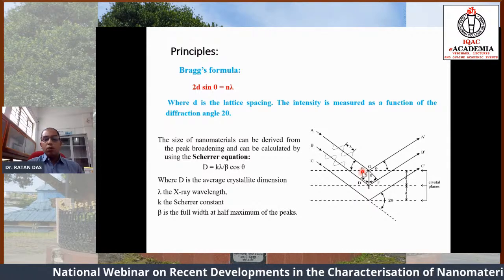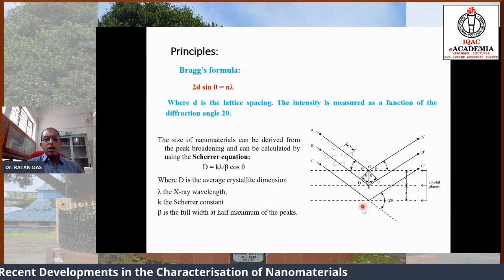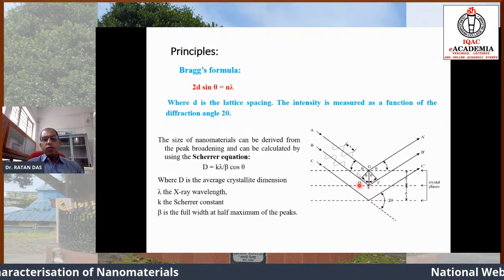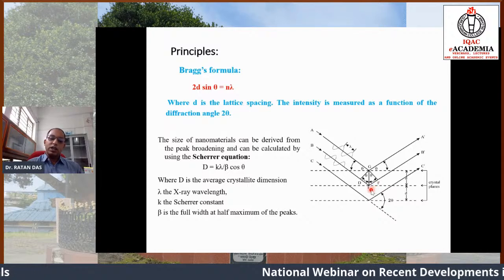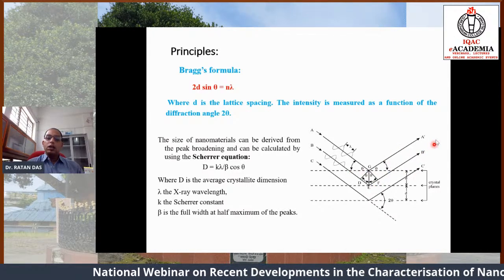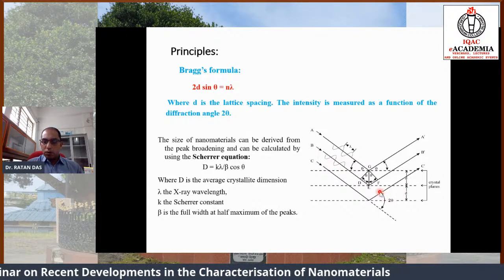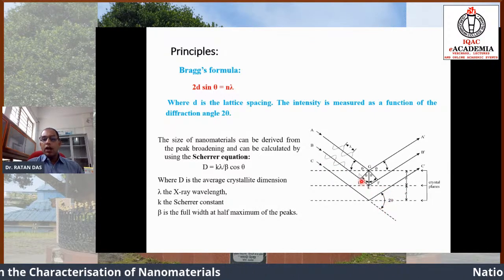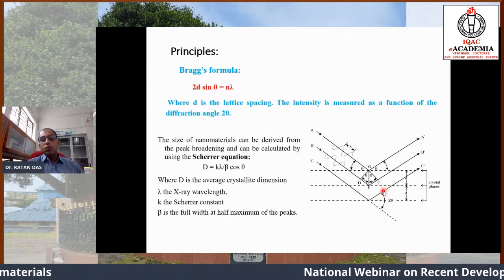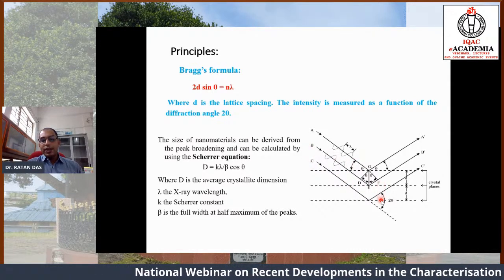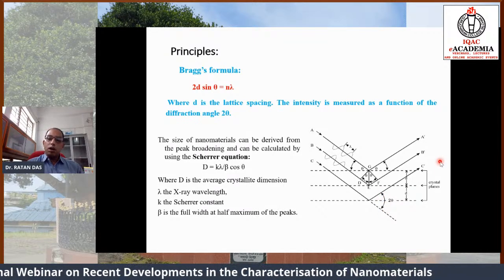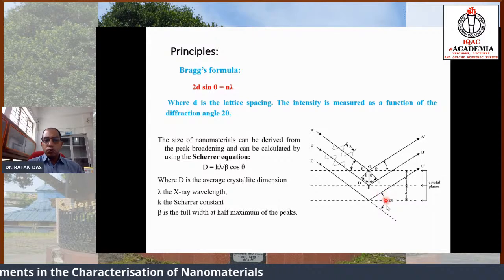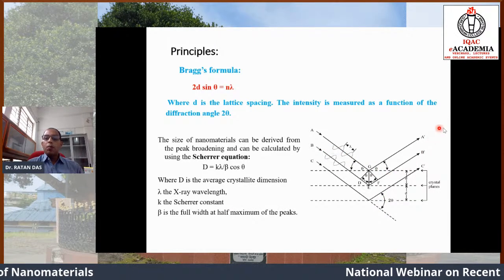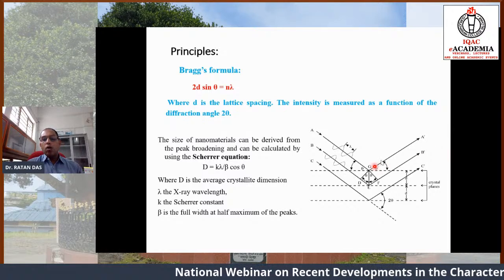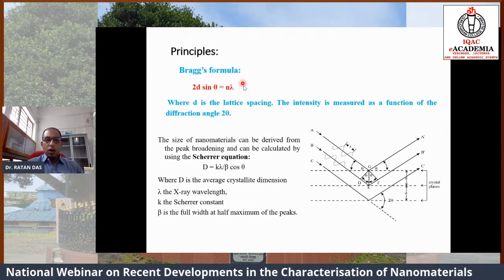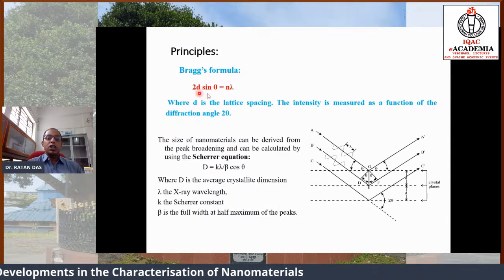The planes may be 110, or 100, or any pattern of planes from which the reflected rays, or rather the diffracted rays, after scattering, may come at a particular twice theta angle. You see there is a twice theta, and theta is the grazing angle. The incident rays make an angle twice theta with the detector, and at a particular value of twice theta, these diffracted rays make an interference pattern, or a diffraction pattern, where they satisfy Bragg's formula 2d sin theta = n lambda.